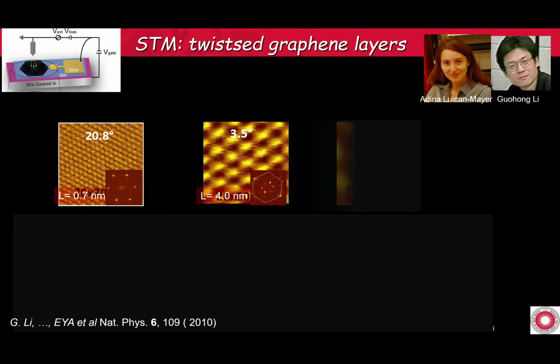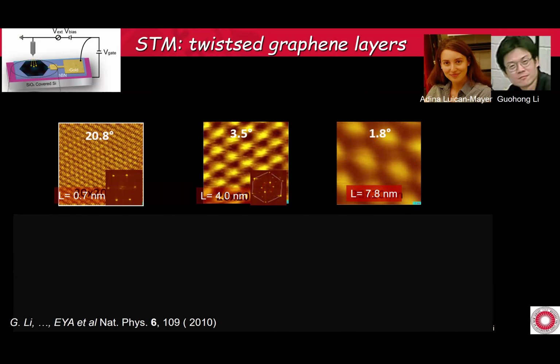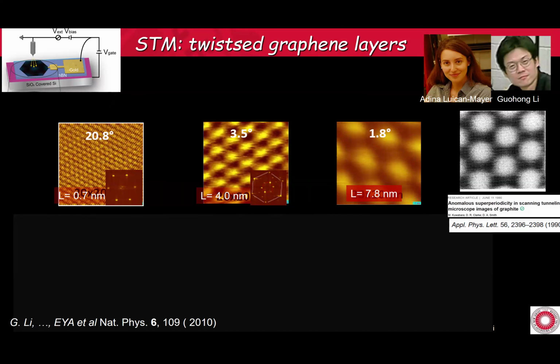Okay, so we came with the STM onto this suspended sample, and at 20 degrees, 3.5 degrees, you see the pattern gets bigger and bigger as expected, like A over theta. We're getting up to 1.8 degrees. So, okay, this is not a big deal. One of the first experiments done when STM was first built by the IBM group was with graphite, and they immediately saw the Moire pattern. No big deal. We knew that they're there. This was known since the 90s.